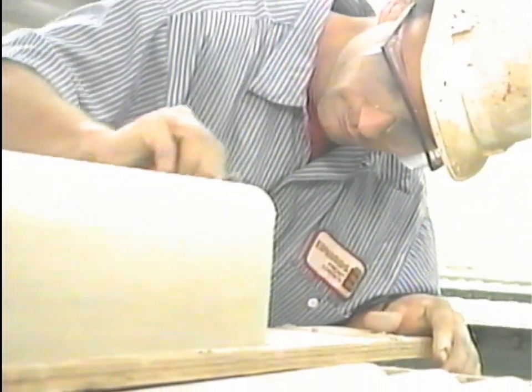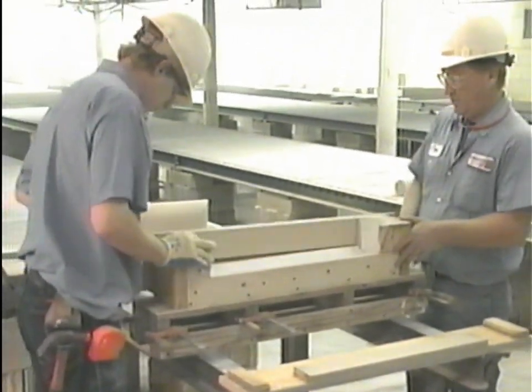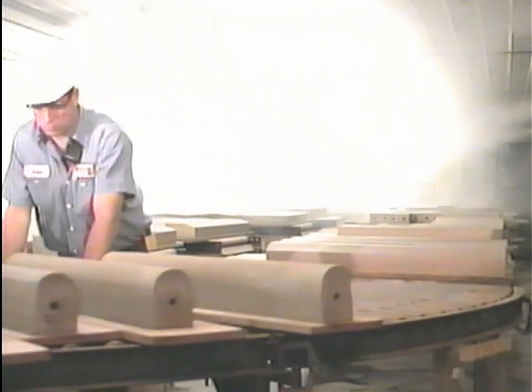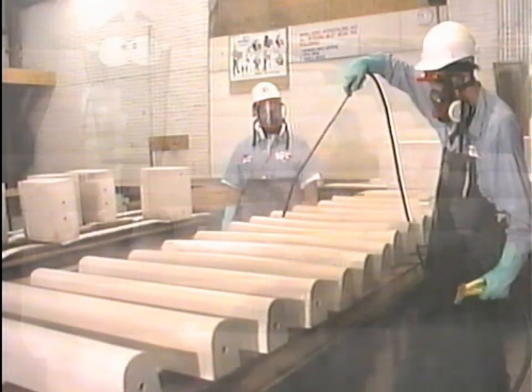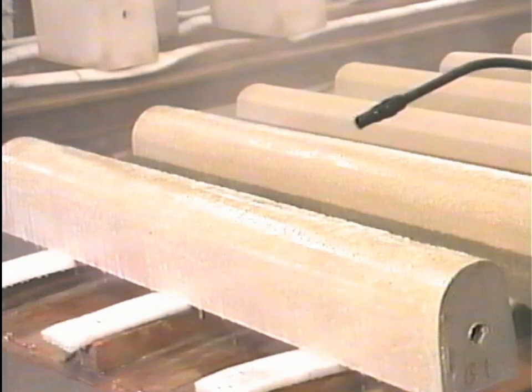The stone is slid onto the conveyor line and the mold is disassembled. Edges are tooled, finished, and dimension accuracy is checked. The stone is immediately put into a 100% moist environment for up to eight hours. The mold is reassembled for continuous casting production. Following hydration, the stone is steam cured overnight, greatly accelerating the curing process. The next morning, each piece is hand sanded to a smooth finish. A mild acid solution is applied to remove the cement skin matrix. The cast stone's color and finish are now completely weather resistant.